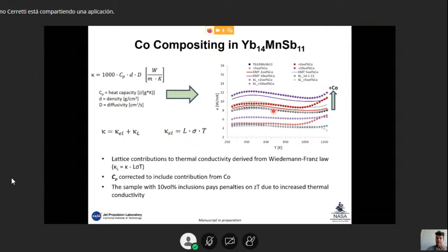Also here, I used the same model I used before to compute what the values of the composite material should have been, using the equation I showed you before. And also in this case, we can see that the expected values are not really in line with the ones that we measured, and that was surprising.